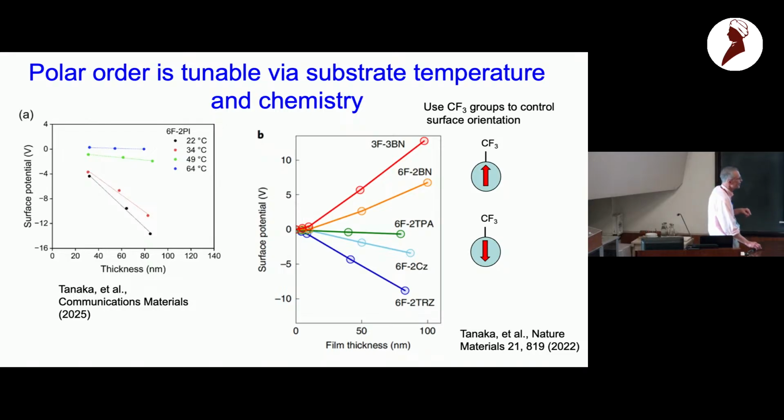So everything in this process is being controlled by what the molecules are trying to do right at the free surface during the deposition process. And then as soon as they're 1 or 2 layers below that, they are stuck because they've lost their mobility. And that's why we can continue to add layer upon layer of these dipoles and get this huge macroscopic dipole.